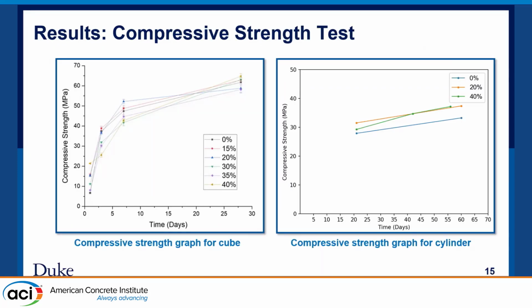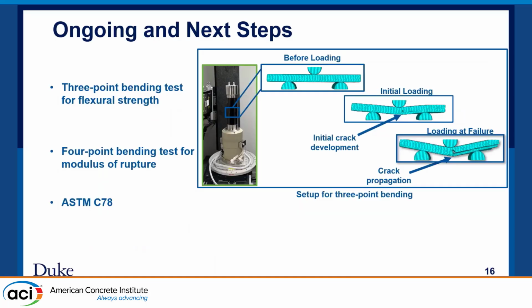And this is the result for the compressive strength test. This is the preliminary result for the compressive strength test. We look forward to using our actual 4x8 concrete samples for this test, as well as we plan to do the flexural strength test for the same sample size for further research. For the ongoing and next steps, we are planning to do the 3-point bending test for flexural strength, and the 4-point bending test for modulus of rupture.